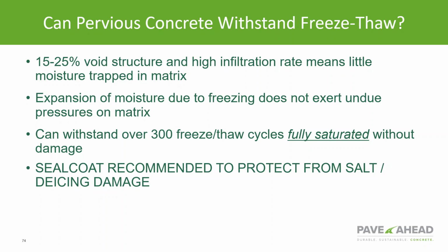That said, the mixes that we use now are so strong, and we have study after study, that you can fully saturate them, and they will go through 300 freeze-thaw cycles completely saturated before they start to show any damage. So this concrete actually works very well in wintertime conditions.